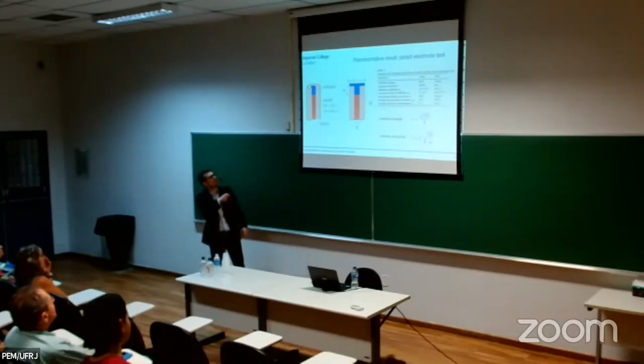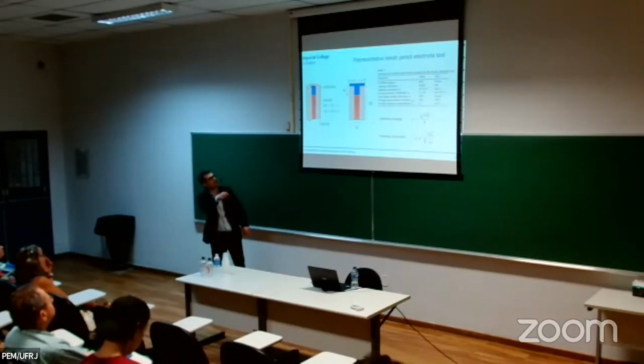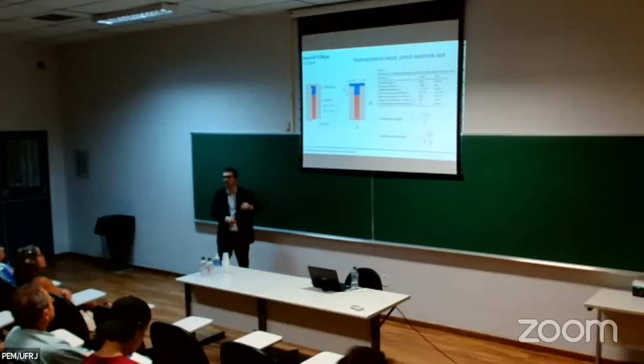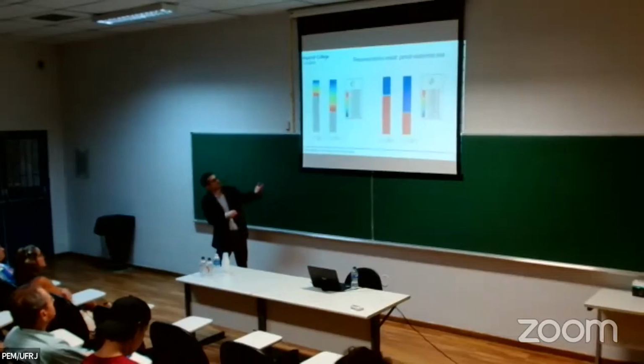This is effectively a 1D problem. You have corrosion of this metal layer, a metal wire, and it's a 1D problem because you're protecting the rest, so it basically corrodes uniformly in this direction. And there are analytical solutions for this problem in the diffusion-controlled corrosion regime. And this is what you see with the model.